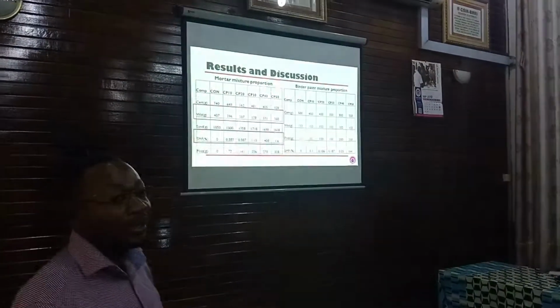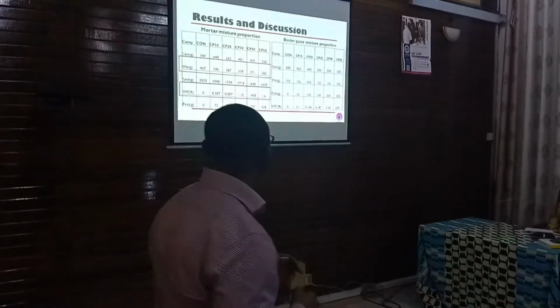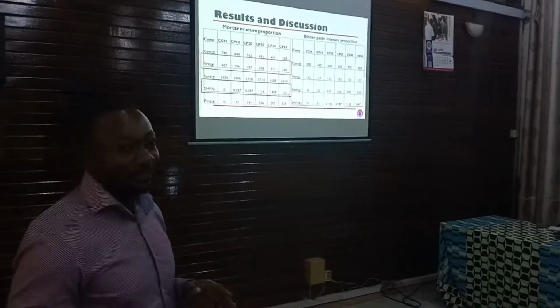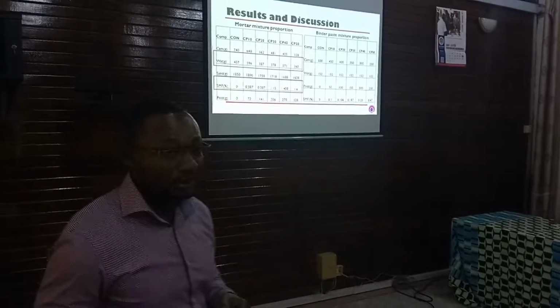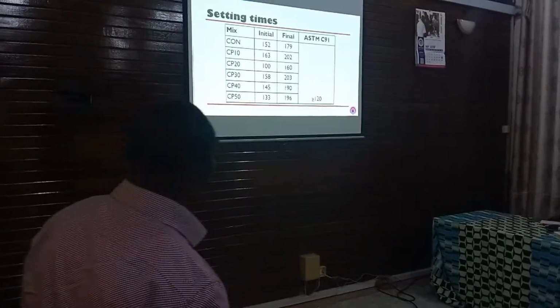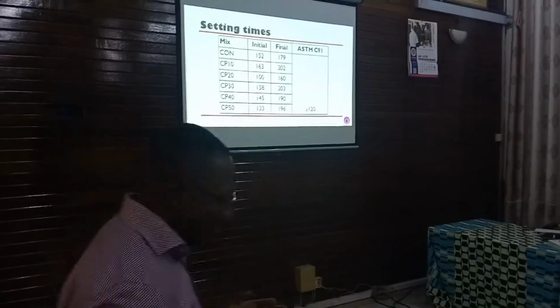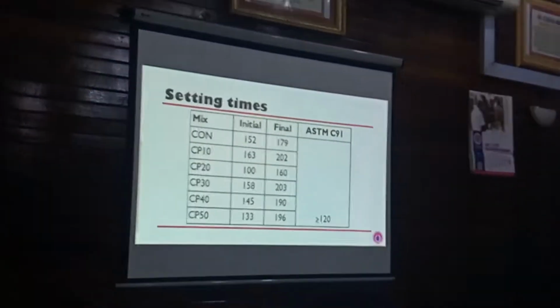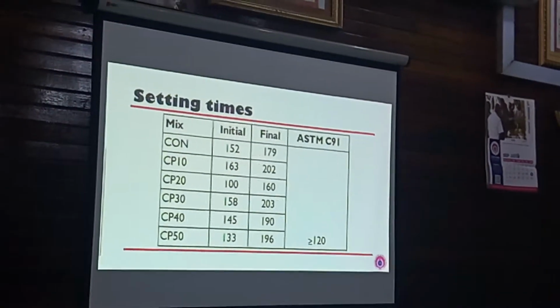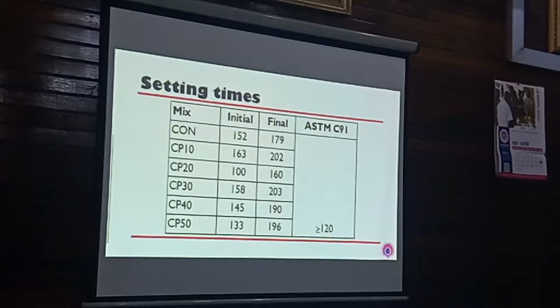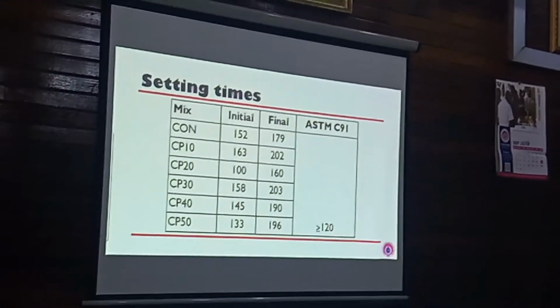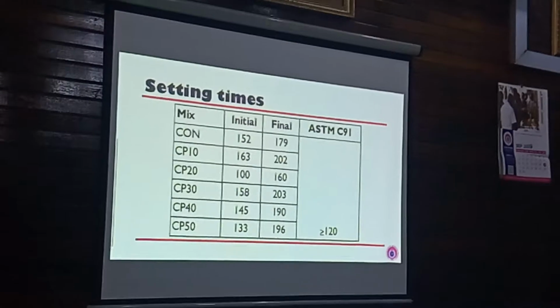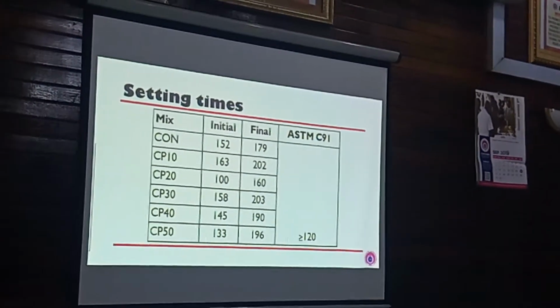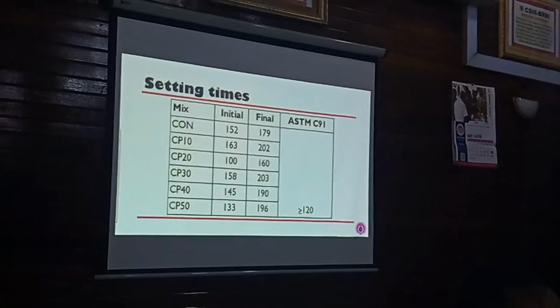And this is also the formulation for the binders. It's always important to show the masses of your mix. Sometimes you see that people present percentages, but mostly it's better to also show the masses that you've used. So these were the results of the setting time. I wasn't so much interested in setting time, but I wanted to get an idea of the material, because setting time gives you an idea, for example, if I talk of initial setting time, that when I add water to cement, some form of interaction starts.